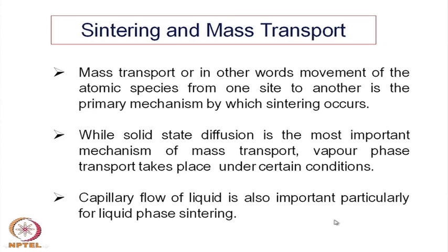There is another mechanism by which mass transport can also take place: the capillary flow of liquid. In case of a liquid, because of the surface tension force and the capillary action, the liquid can move from one place to the other, and that also is a form of mass transport. So, capillary flow of liquid is also important, particularly for liquid phase sintering.